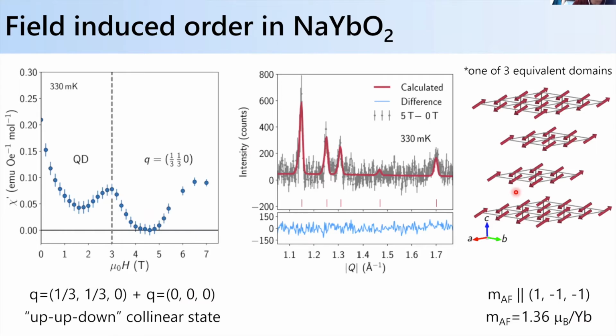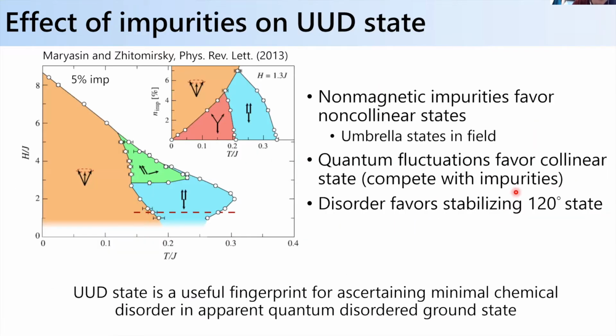And so why is this interesting or important? It's interesting because the up-up-down state has been studied for a long time, and the effect of impurities on the up-up-down state has also been explored theoretically. From the Heisenberg model of the system, if you were to add impurities, in this case 5% non-magnetic impurities on the triangular lattice site, what it does is destabilize the up-up-down state and push it.